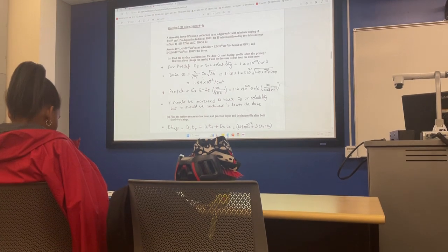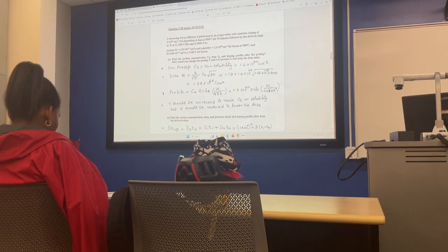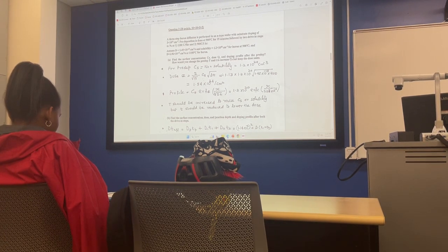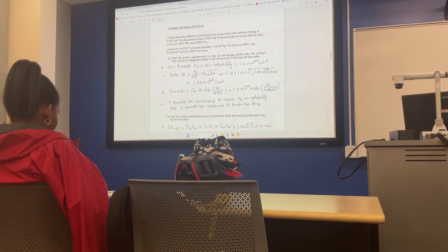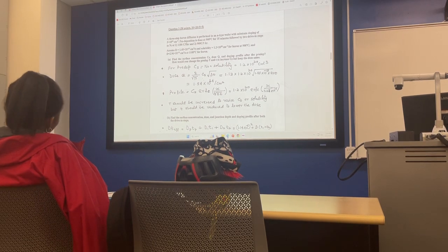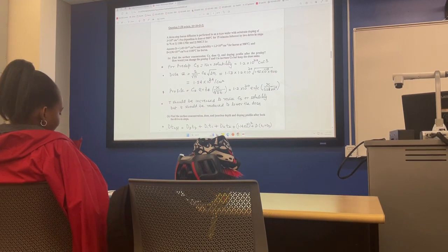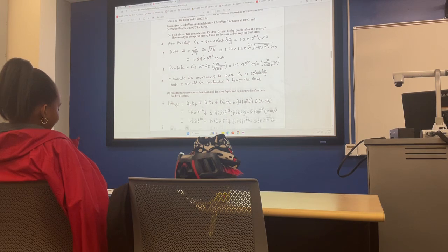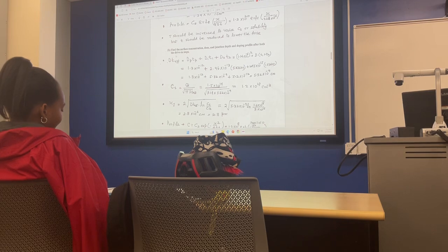But then I want the dose the same. So if you want the dose to be the same, your Dt product has to be similar, so you have to cut down the time. So you reduce the time and you increase the temperature. So that way, dose is related to Dt. If I increase my D, I need to reduce the time, and that way my dose remains the same, right?